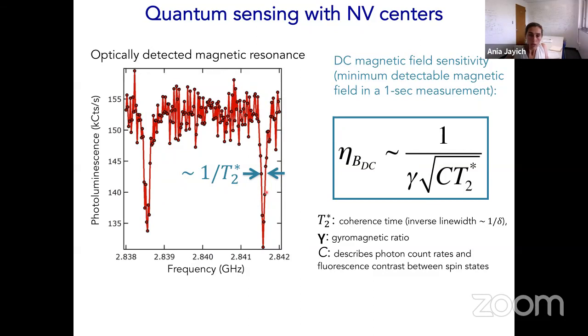But here, the line width of this transition is on the order of, say, 100 kilohertz. And that line width is inversely proportional to the T2 star, the quantum coherence time of the NV center. The longer the T2, the smaller this line width, and the more sensitive the NV is to small changes in magnetic field.